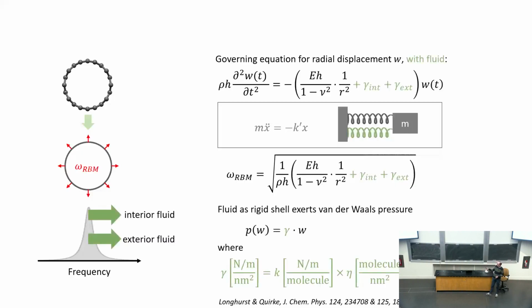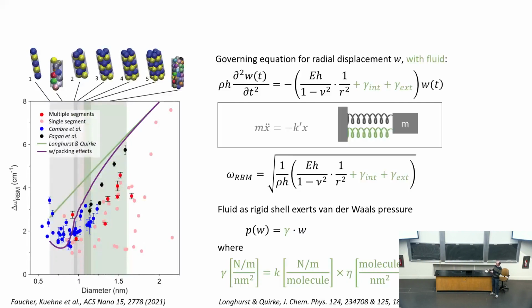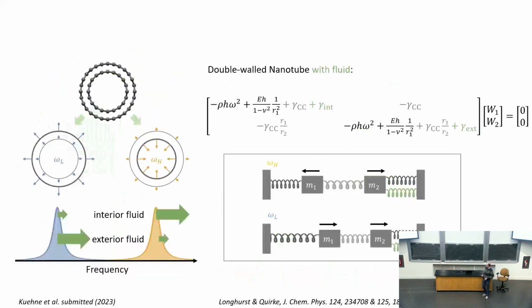Now, if you put a fluid on the inside or the outside, this law is modified a bit. Effectively, the spring constant increases in strength, and that shifts your RBM frequency in the same direction, irrespective of where you place the fluid. This expression also allows you to extract the density. You can decompose this coupling constant as a coupling constant per molecule and a molecular density. So it's a tool to get density, but it's very different from PL. Here we look at different experiments done as a function of diameter where you get this shift, and you see a well shape emerging at low diameter, which we think is related to molecular packing effects.